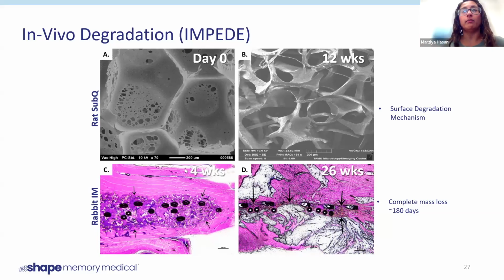And our degradation was further confirmed in a rabbit intramuscular implant, where on the bottom right, you see the foam that's kind of highlighted in purple. These black dots are the coil. So that's really not going to go away. But what we see at 26 weeks is that the foam has mostly gone away, and that aneurysm area where the foam was deployed has shrunk quite a bit. And we observed that at 180 days, there was complete mass loss. So there really was minimal foam, you don't see a lot of the purple foam that's available. And you can just see the regular tissue, the collagenous tissue around.